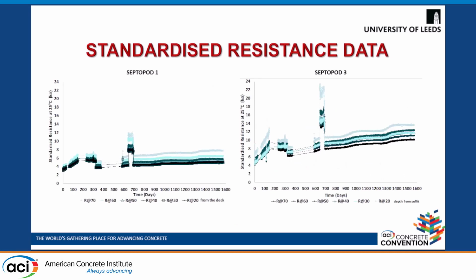So the huge variations which were seen earlier are now reduced, and we can see that even though there is some missing information in the data, overall the resistance is increasing with time. However, there is a drop in resistance around the end of year 1, after the repairs. This was because there was a leak in the repairs. Once these repairs were done, the resistance started to increase again.